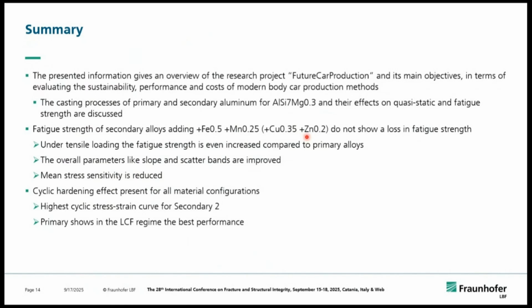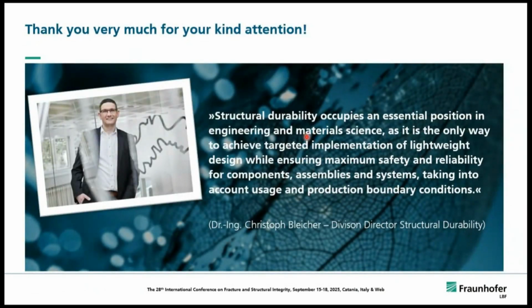And I showed you also the cyclic hardening effect, that we lose a little bit in the LCF regime. This might be interesting in most cases, I would guess. We're not talking about high elastoplastic loads on the car body parts when it comes to a total strain of 2 or 1.5% total strain. So overall, we could not state that we have really a problem with this alloy with adding some elements here, and we could give a good estimate, I would say, for further developments in the direction of secondary alloys for aluminium.